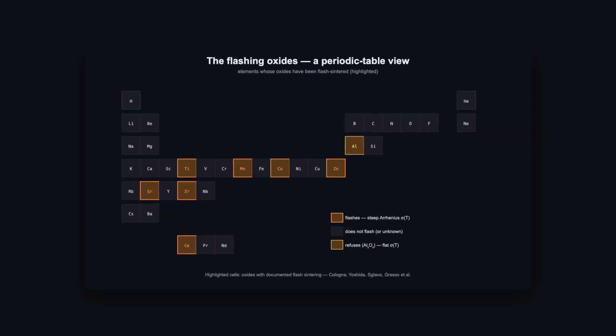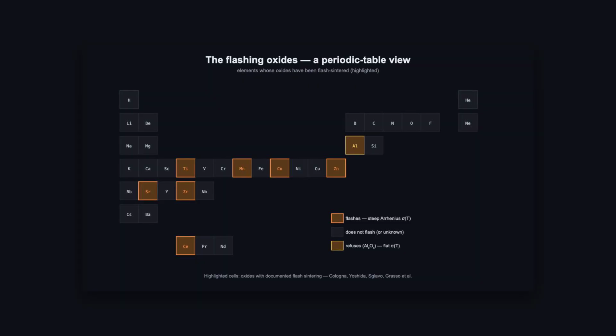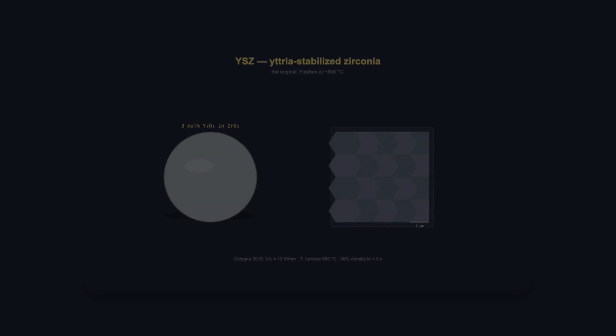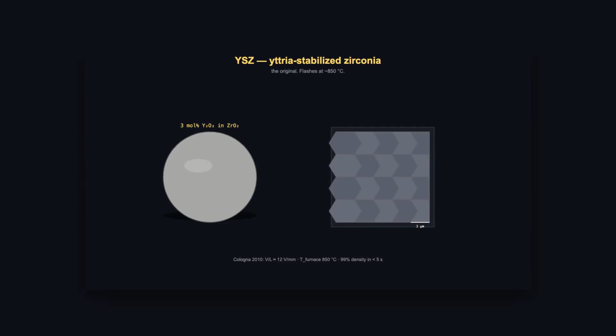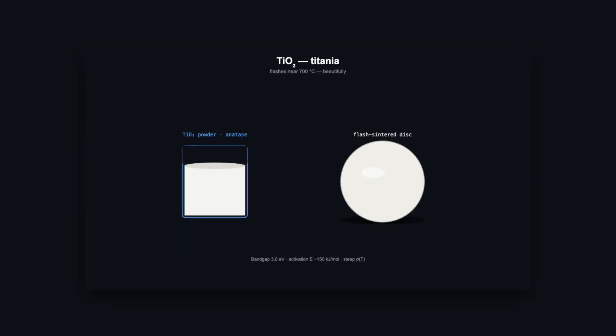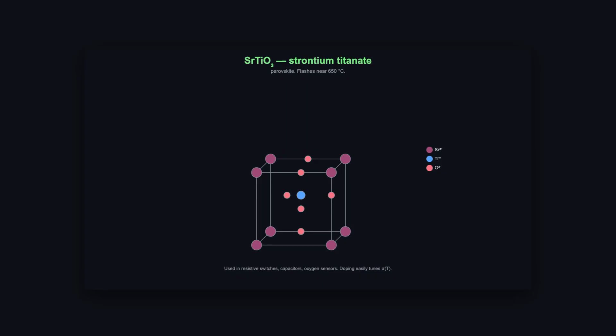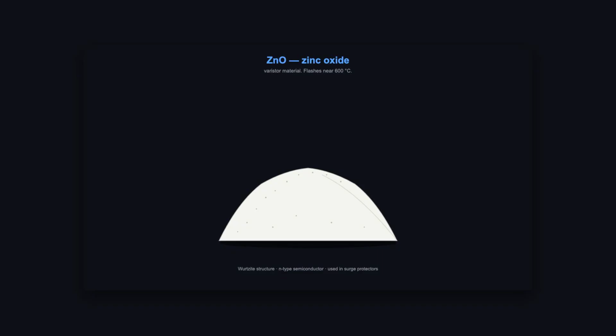Back to the gate, Arrhenius. Every ceramic has a fuse temperature written into its conductivity curve. Some are short fuses, some are long, some have no fuse at all. Yttria-stabilized zirconia, the original, steep Arrhenius curve, flashes around 850 Celsius. Titania, titanium dioxide, flashes near 700, beautifully. Strontium titanate, 650. Zinc oxide, flashes near 600.